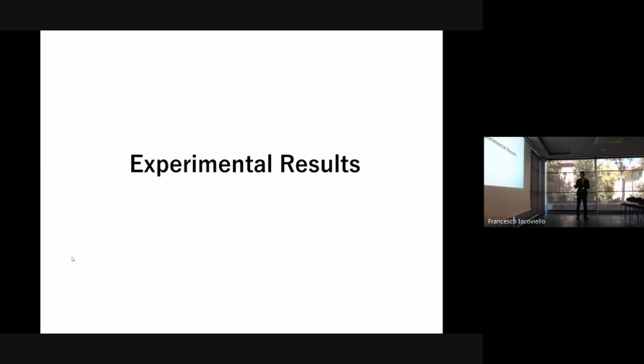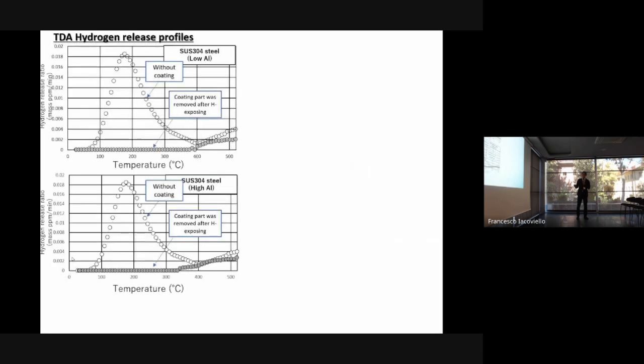Experimental result. This graph shows the TDA hydrogen release profiles of SUS 304 steel, austenitic stainless steel, with low aluminum and high aluminum. This graph shows without coating and with coating. I want to explain briefly about the graph.